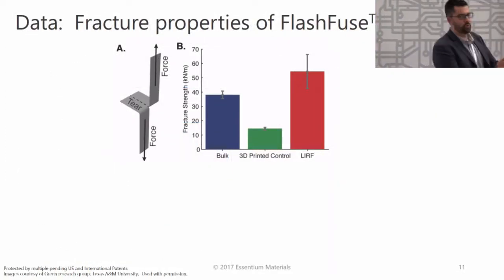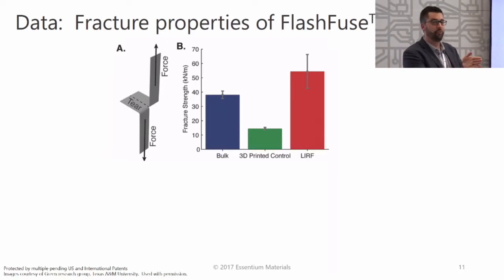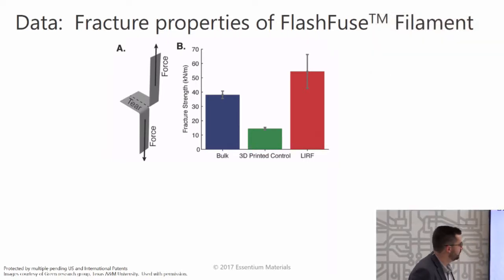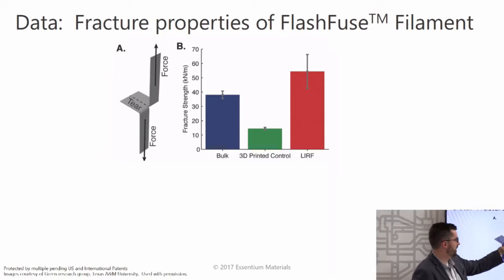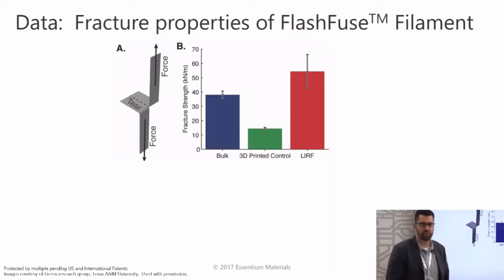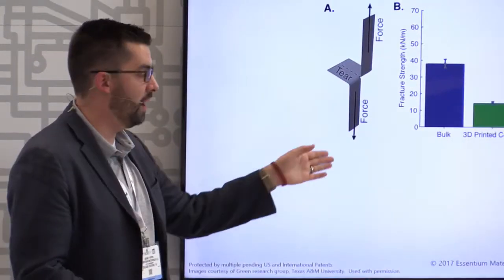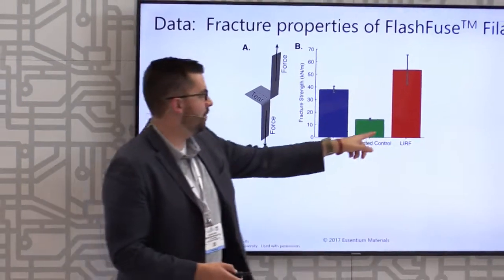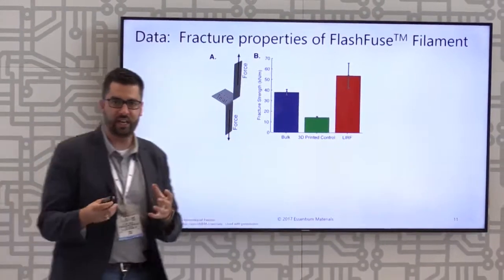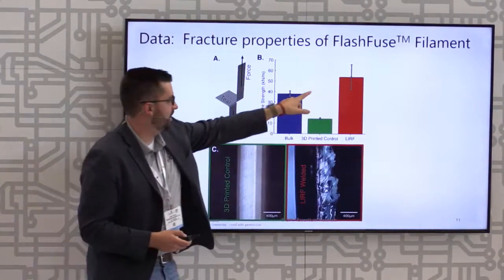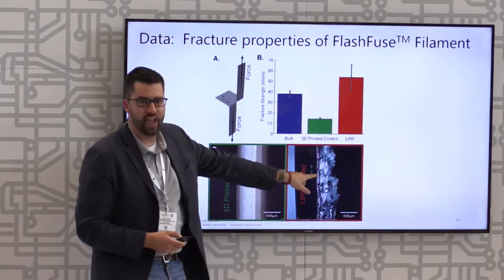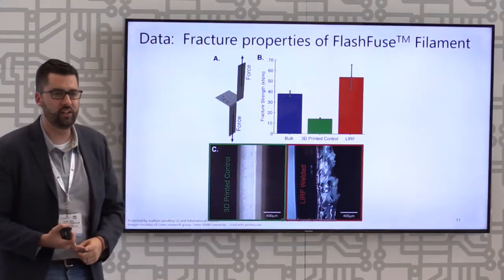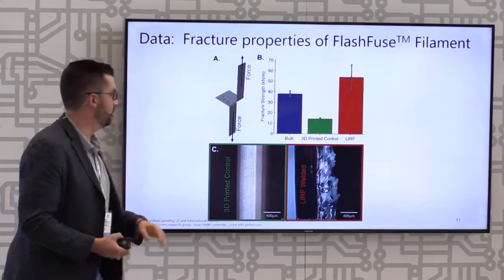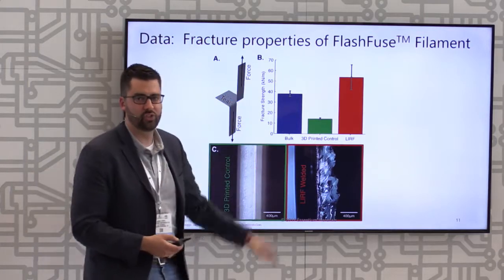So what does that mean for mechanical properties? What we look at is the mechanical properties in between the joint from a fracture toughness standpoint. When you look at bulk polymer, you basically have fracture toughness right in this range. 3D printed parts, the fracture toughness dips quite a lot because you have that really poor weld. And then with our local process of introducing the heat at the joint, we actually get not only improved fracture toughness, we get a taffy type failure. So you get increased ductility, increased strain at break, and a dramatic improvement in the whole part isotropic properties.